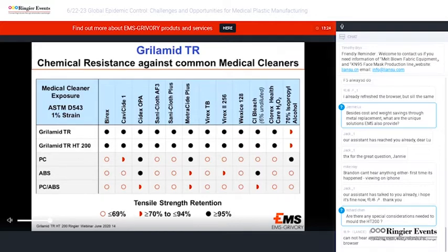If we look at the polymer materials tested, let's start with the bottom three: polycarbonate, ABS, and a polycarbonate ABS blend. Here we can see that all three of these grades show a poor resistance, excluding a few exceptions. On the other hand, Grilamid TR and Grilamid TR HT 200 have an excellent resistance for all tested cleaners apart from IPA at 70%, where we have limited resistance.